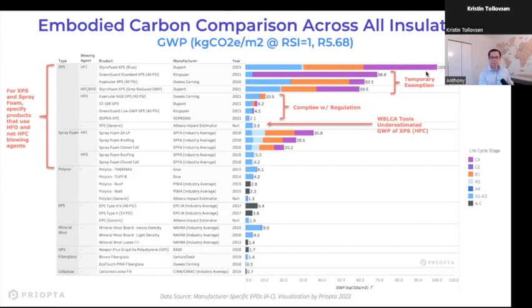Now, since then, in 2021, Canada introduced new regulation to limit or ban the use of these HFCs. And so all the major manufacturers for XPS started producing lower carbon variants. Now you can see this is the new batch. These are using hydrofluoroolefins, HFO. These are lower GWP types of blowing agents. These are now in the 2 to 10 kilograms of CO2 per meter squared range. So you can see that's a big difference from 100, right?